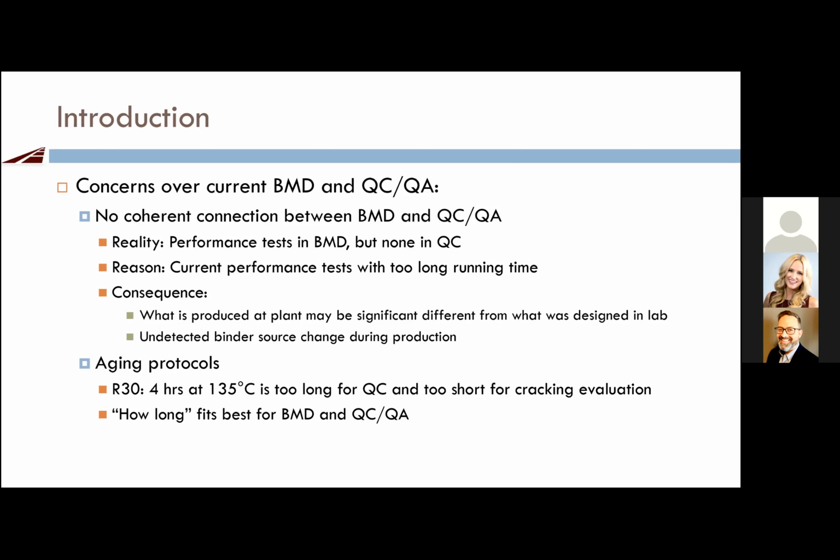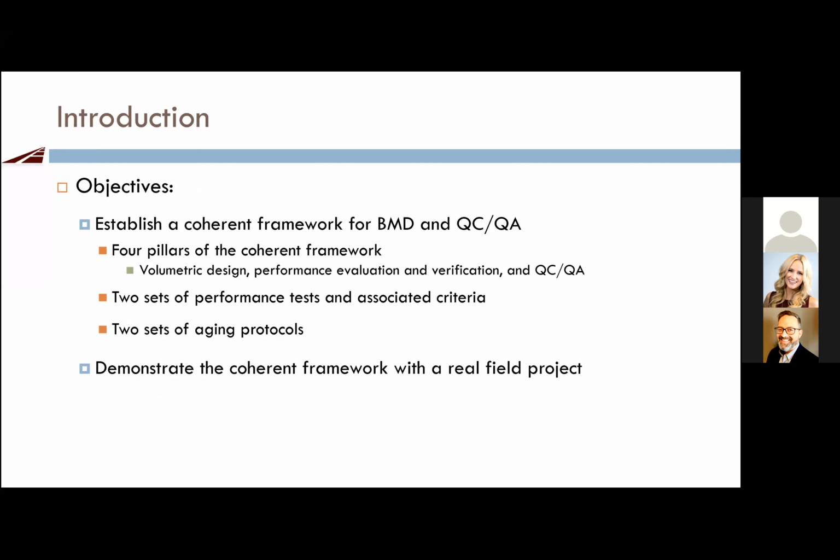So, but 4 hours at 135°C is really too long for QC, but maybe it's too short for cracking evaluation. So what we really need is a proper aging protocol that fits best for both BMD purposes and QC/QA purposes. So those are the two major concerns with the current BMD and QC/QA process.